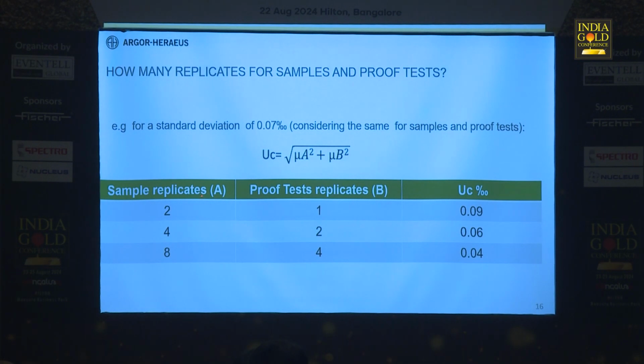If you double the number of replicates, we have 4 replicates, 2 proof tests, we get 0.06. If you double again, we have 8 replicates, 4 proof tests, and a final uncertainty of 0.04. These are very important numbers, because if you consider one sample, if you want to get 0.04, you must prepare 8 samples and 4 proof tests. That means for one sample, I must do 12 analyses. It's a lot of analysis.